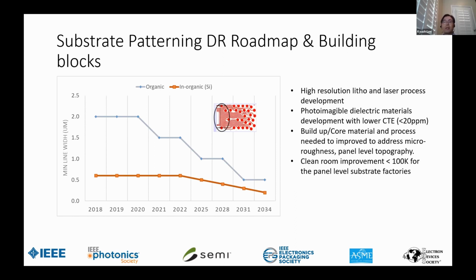For silicon interposer base, scaling the line and space is much easier, given that we are using the well-established silicon back end. But for organic substrate, it is relatively challenging since it has additional variables such as material shrinkage and topography. To continue to scale the line and space in the organic substrate, which is typically at panel level, like 510 by 515 or 600 by 600, we need to improve the material, improve the topography, to enable fine line litho resolutions.